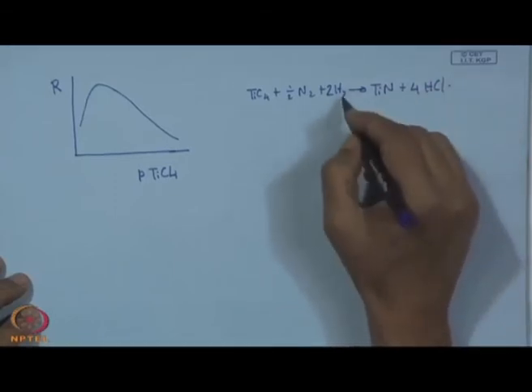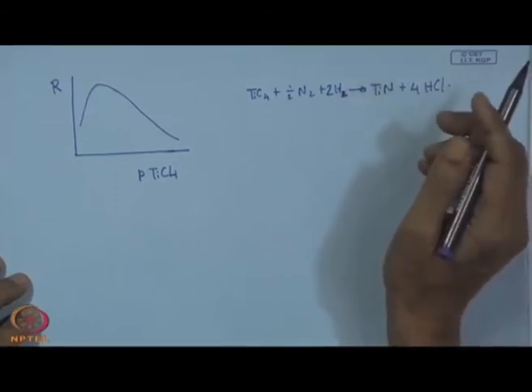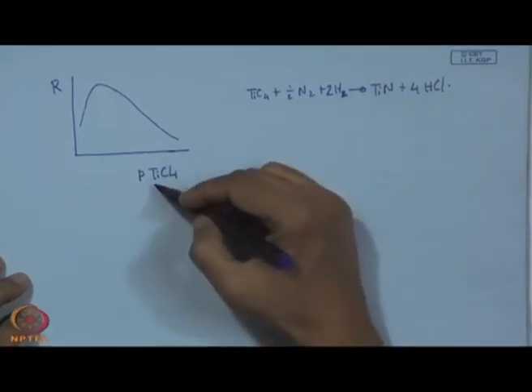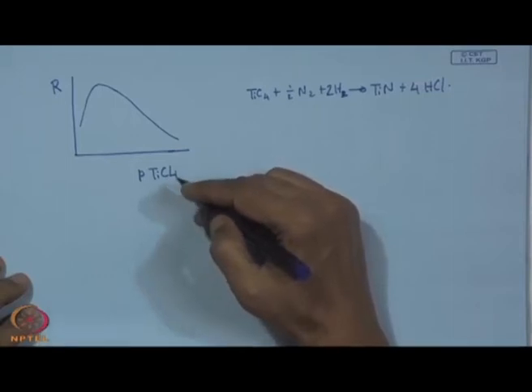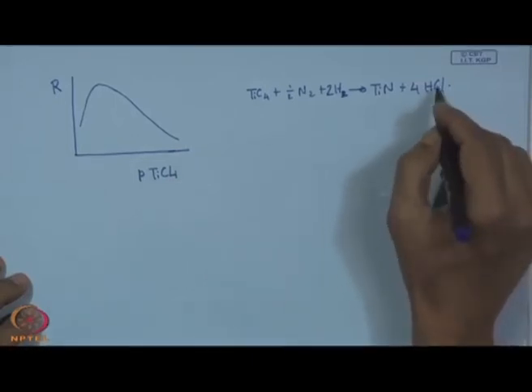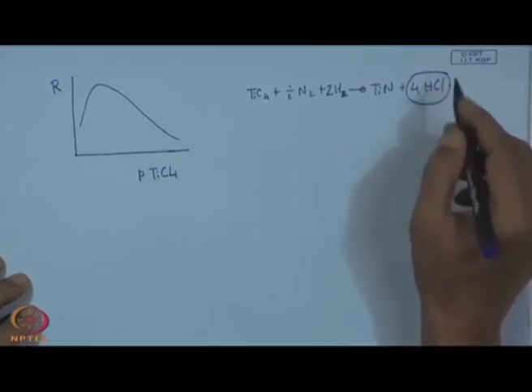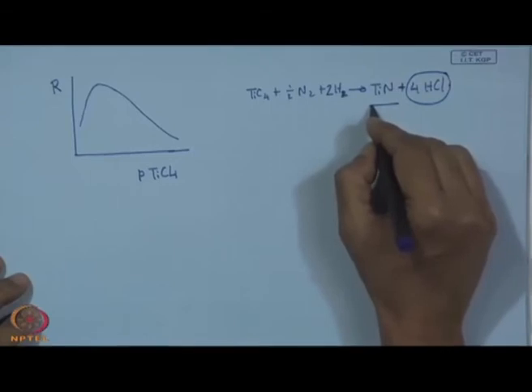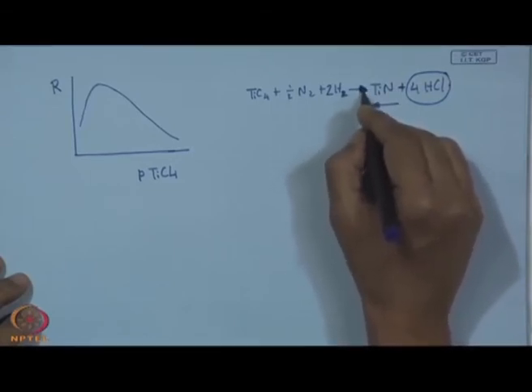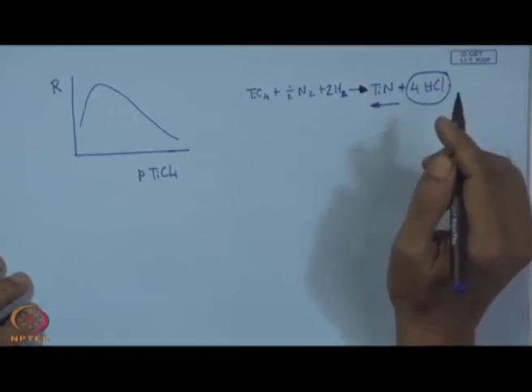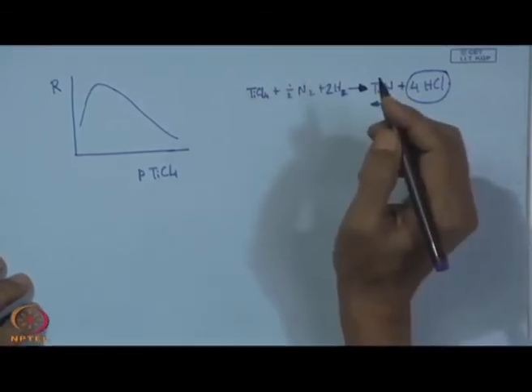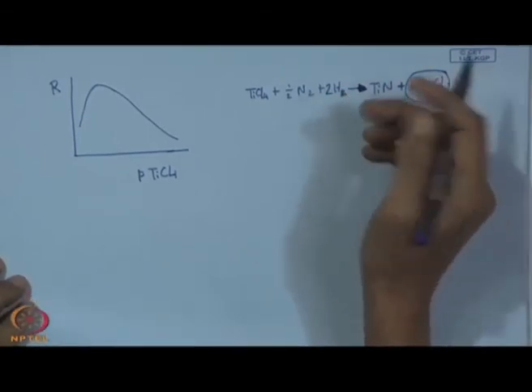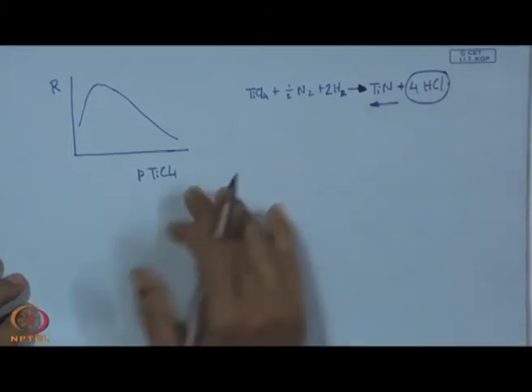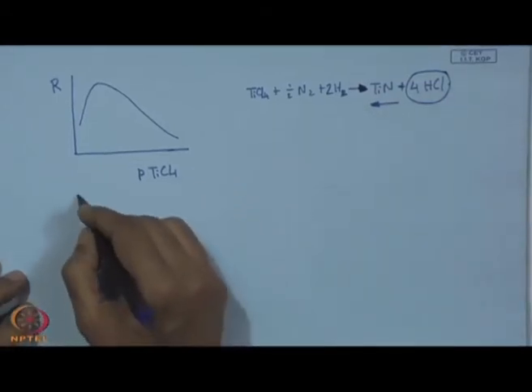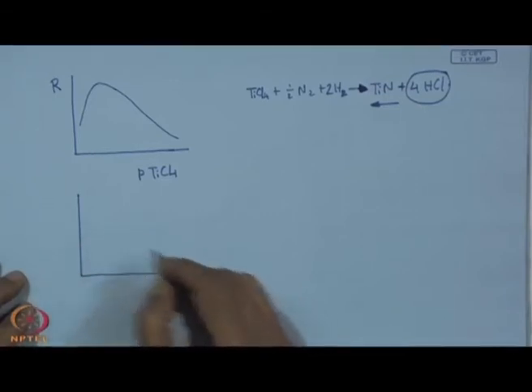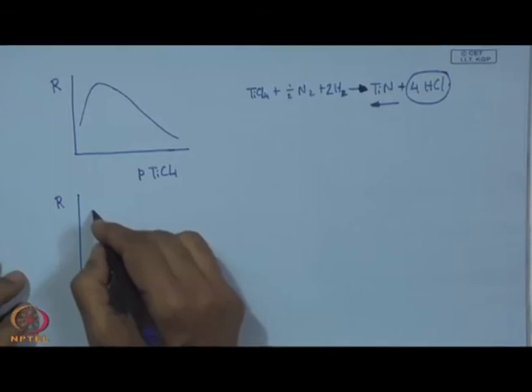So, without increase of H2 or other parameters, if we keep on increasing the partial pressure of titanium tetrachloride, P_TiCl4, then there will be too much formation of HCl and it will revert the reaction in this direction, and the reaction in the forward direction will be seriously affected. So, if P_TiCl4 is increased without touching hydrogen or temperature or any other parameter, then we can see such a trend.